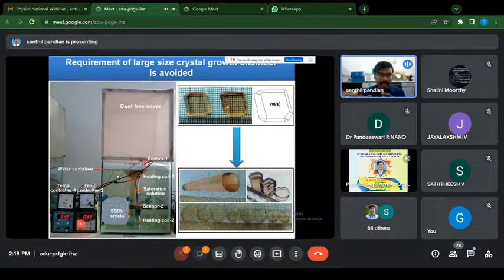For growing crystals by this SR method, if we wish to install it in your UG, PG or PhD laboratory, you need only 5 to 6,000 rupees. Within this amount, one can construct all these small wire connections and the glass ampoule setup. You need only a 1 feet by 1 feet water bath. This is nothing but a normal fish tank. Then you have to buy one glass ampoule and select the inner and outer diameter at the top and bottom portions. It depends upon, as I told you, the solubility and the material you have selected for crystal growth. Then you need 2 RTD temperature controllers, 2 ammeters and 2 transformers. So one can easily construct this experimental setup in your laboratory.